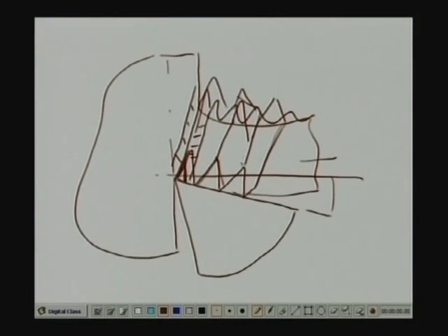This happens while machining titanium alloy by carbides, where such gaps remain and these are all segments connected over a small area. Now, if you apply a little pressure or if the rake is negative further, then this will break into pieces and come out as segments like this, of uniform size and shape. This is the reason or the condition when we get discontinuous chip of regular size and shape.